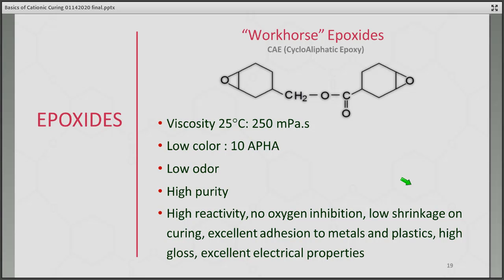It's a relatively low viscosity material, 250 millipascals at 25 degrees centigrade, low color, low odor, very easy to obtain in high purity. And some of the characteristics which really lend itself for it being the workhorse epoxide is that it's highly reactive. You get no oxygen inhibition, which is similar to other cycloaliphatic epoxides. There's very low shrinkage on curing. You get excellent adhesion to metals and plastics. It tends to cure in a high gloss and has very good electrical properties.